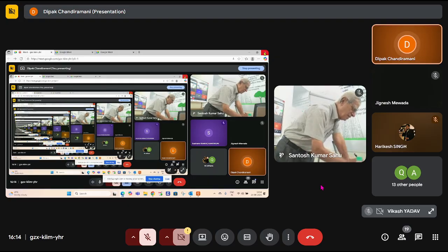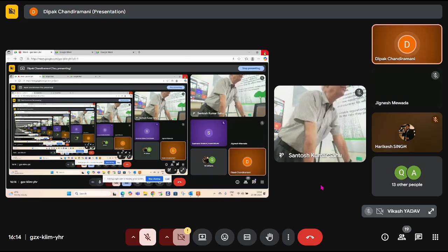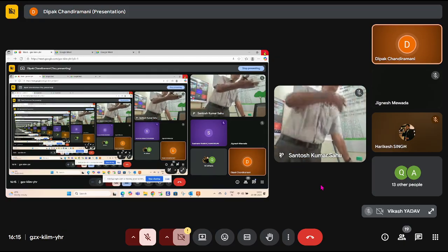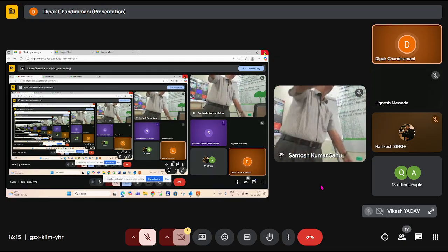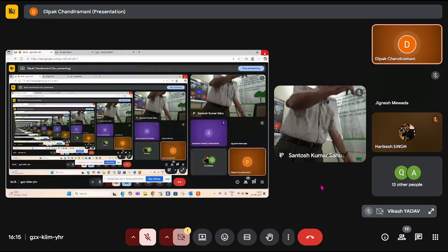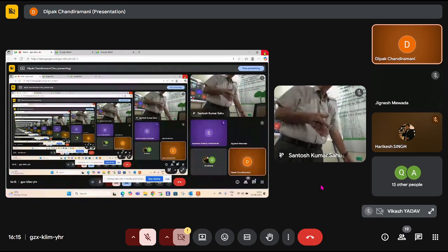Heat treatment for stainless steel and holding temperature: 1050, plus or minus 50, for solution annealing. I showed you the structure of a pure austenite and of a sensitized austenite. Now you have got sensitized, put it to 1050, hold it for how long? One hour per inch at least, so that all the carbides go into solution, and then you quench it.